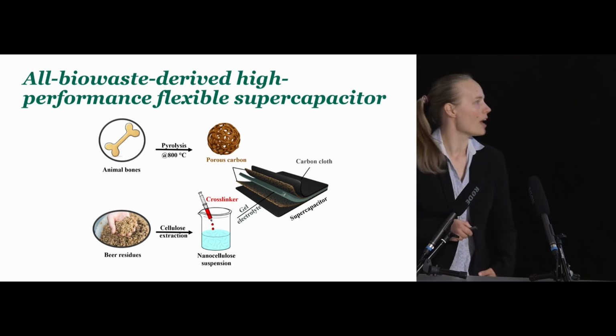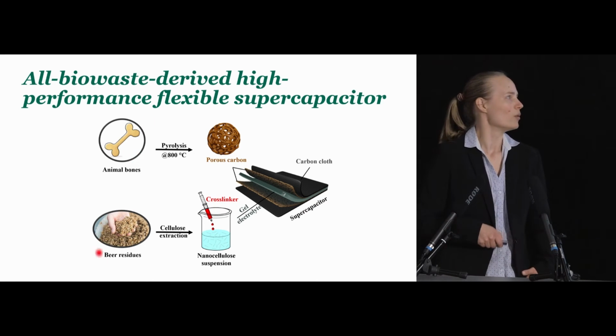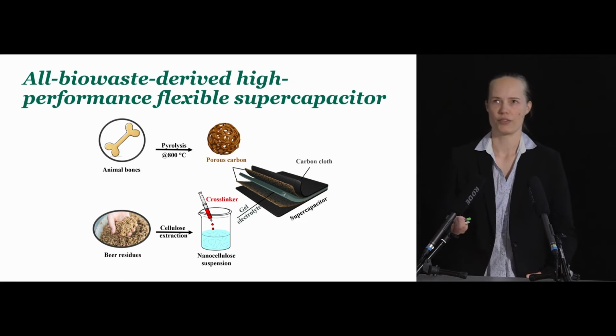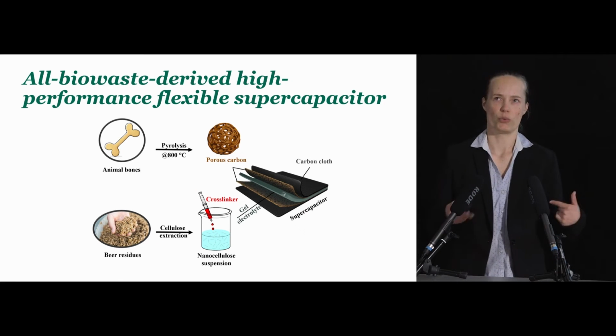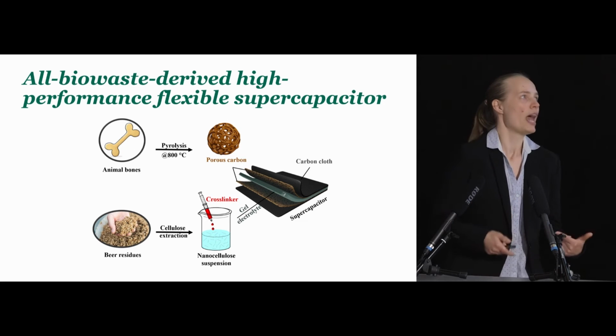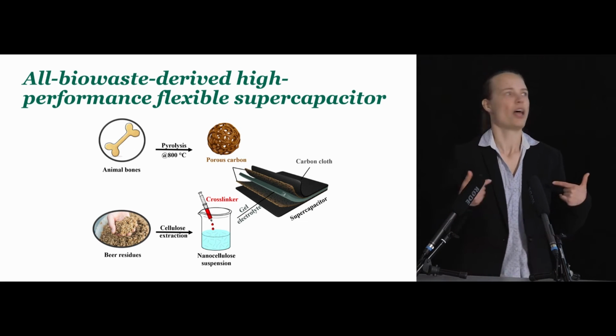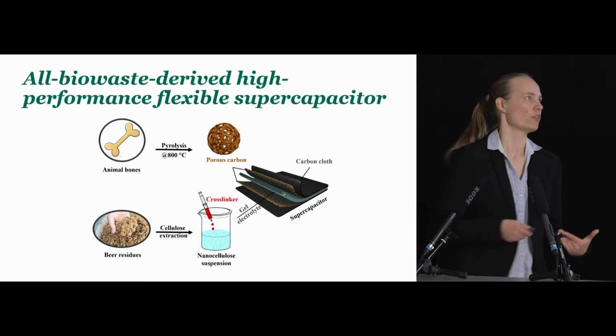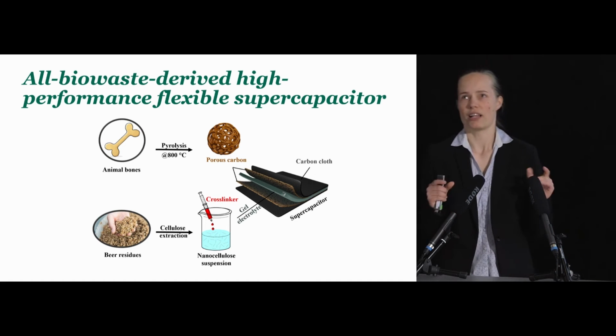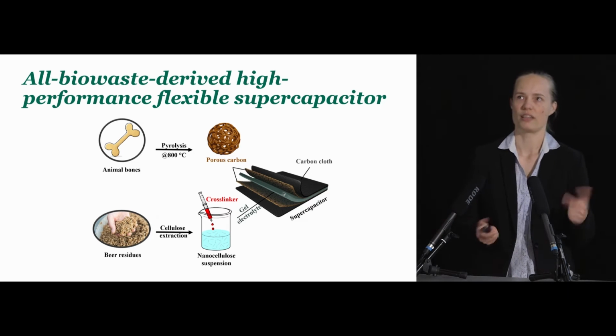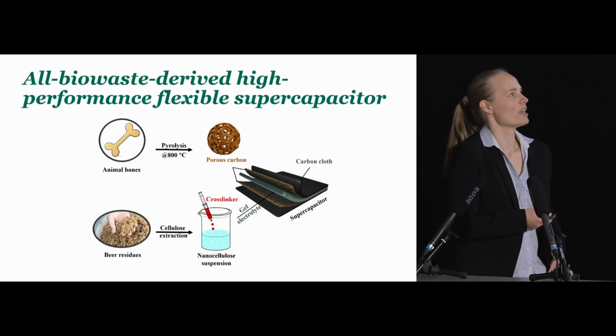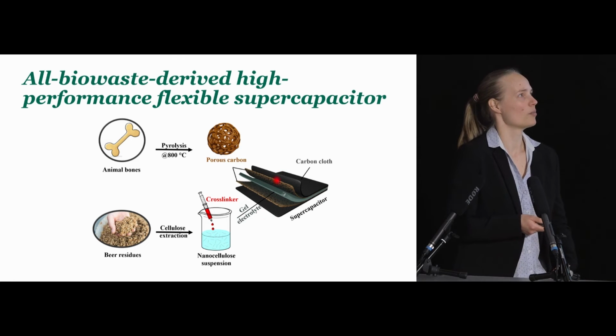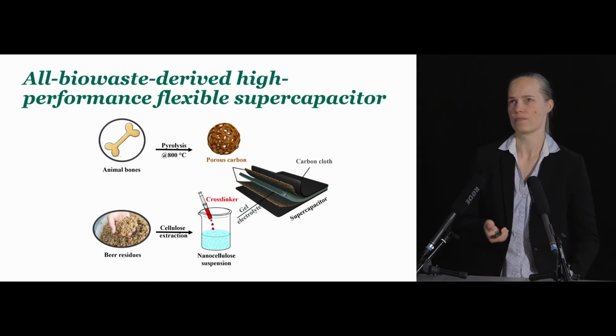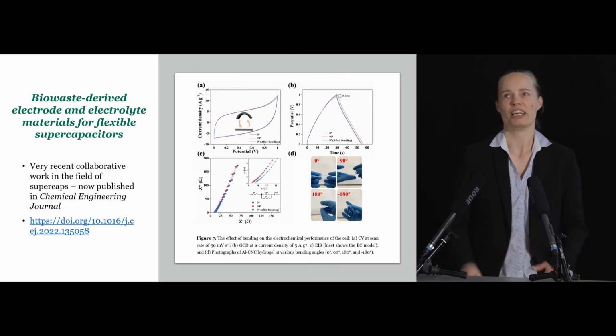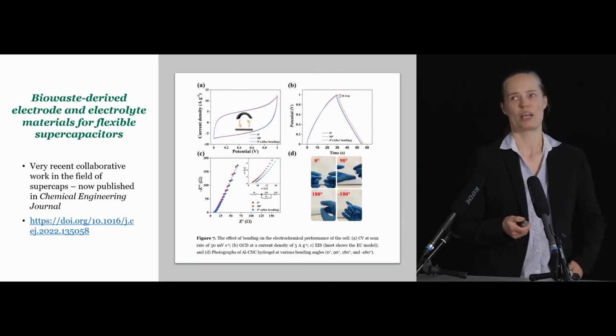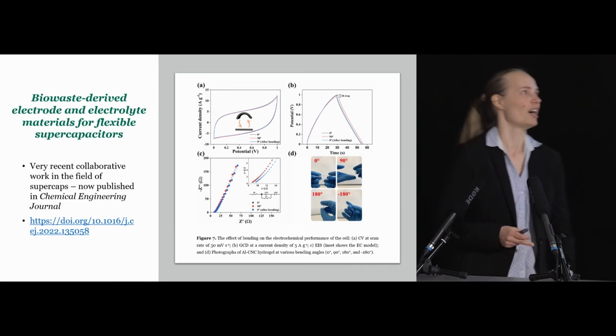Now, at the same time, for the electrolyte, we started from brewer's spent grain, so brewery residues, out of which cellulose nanocrystals were extracted, and then these cellulose nanocrystals were physically cross-linked with the help of aluminum nitrate. This resulted in a very nice ionically conductive and compact gel that could then be compressed between these porous carbon electrodes.